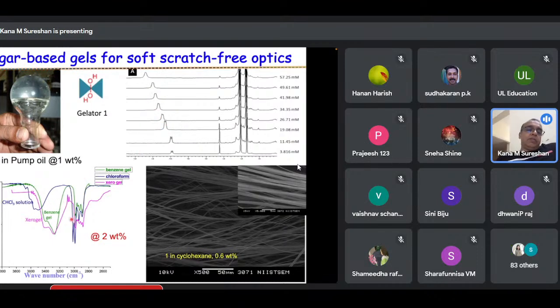And this is, of course, another technique called infrared spectroscopy. And here also, we have a signature for this hydroxy group. This is here, actually, this big broad peak. And this is in the chloroform solution. This is in the gel form. In chloroform solution, the peak is around 3,600 centimeter inverse. But in gel, it is shifted towards a lower wave number, 3,200 or so. So this also says that it is due to this hydrogen bonding.